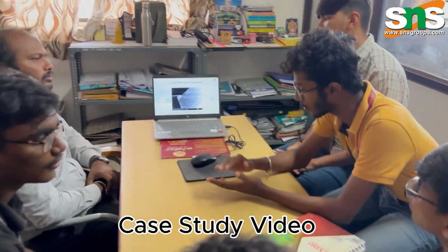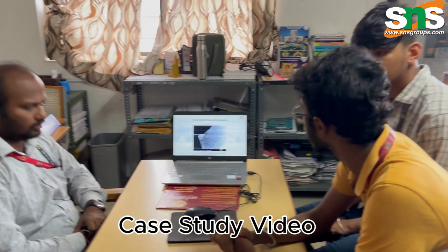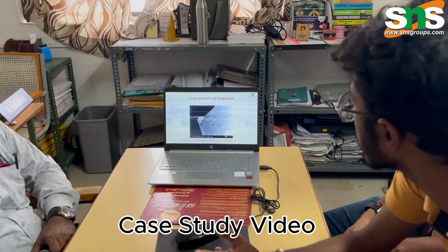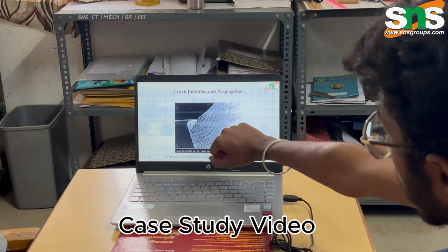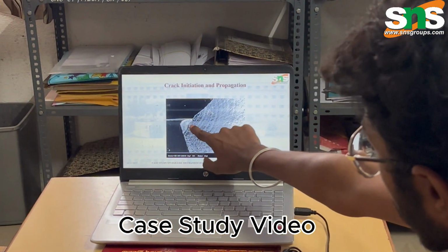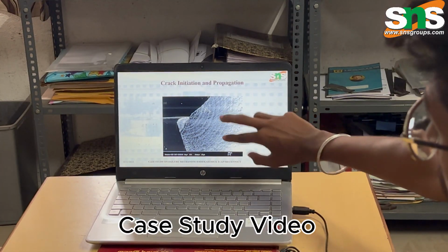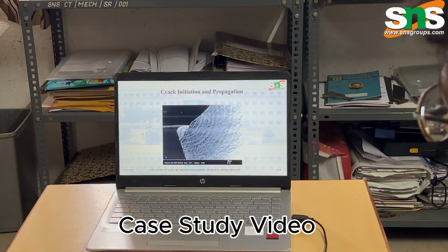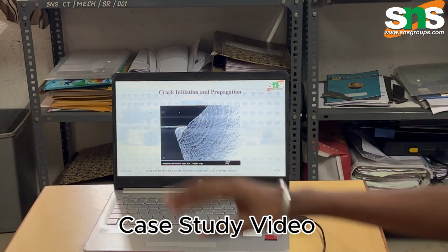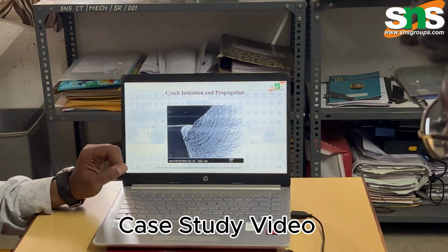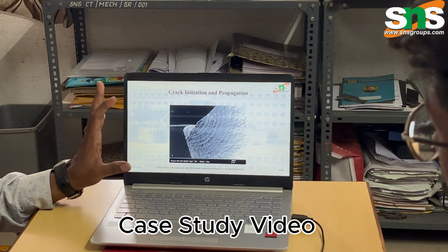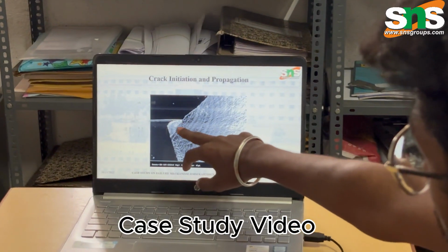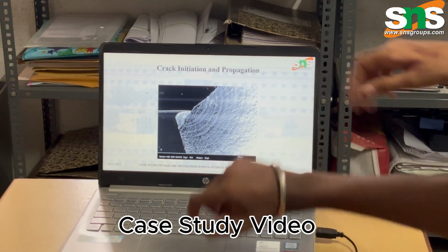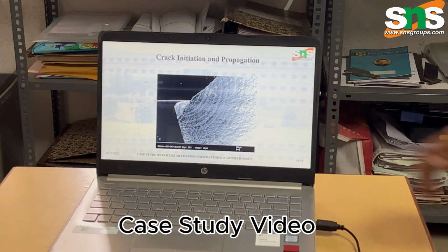We have gone through major processes such as SEM and TEM examinations. In the SEM and TEM examinations we have seen that the crack initiation started here, and then the crack propagated. This is the cause where the gear failed. Where is the crack start area? The start area is here, at the tip, moving towards the outside.